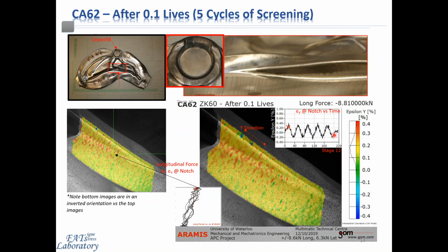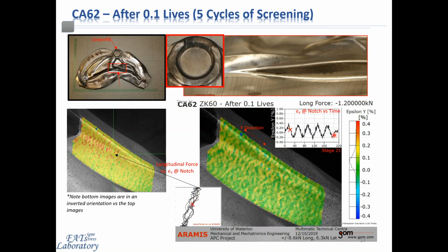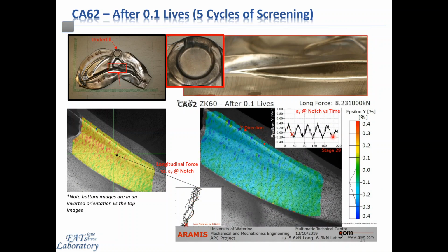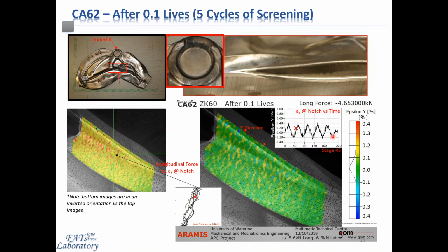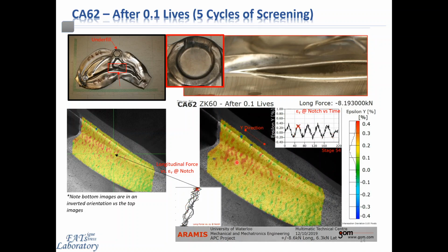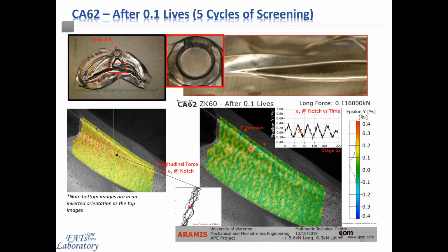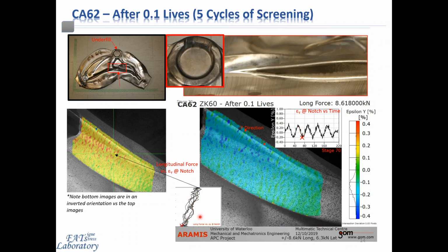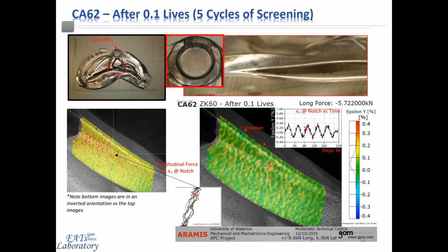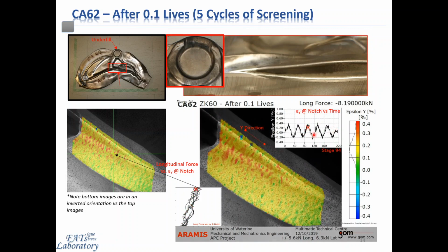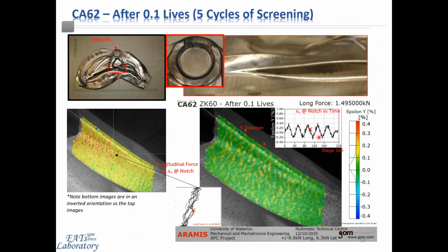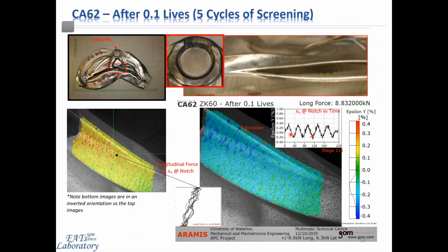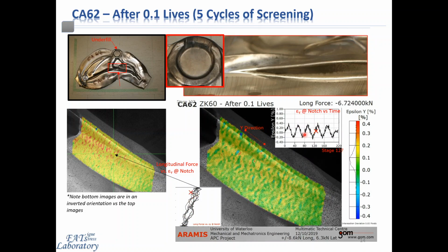Now tracing the exact same information for 5 consecutive cycles, we can appreciate the repeatability of this novel digital image correlation technique for defect detection, as we can trace the same point to have virtually identical hysteresis shown here for 5 consecutive cycles, and then it returns back to 0 as no fatigue crack is nucleated yet. We can see the evolution of the strain versus number of cycles here, and we can see the peaks and valleys are approximately the same for each cycle.